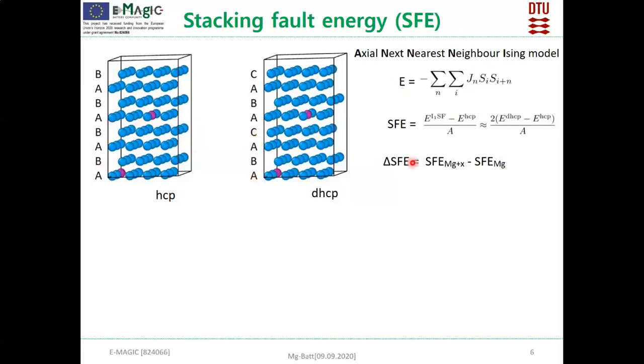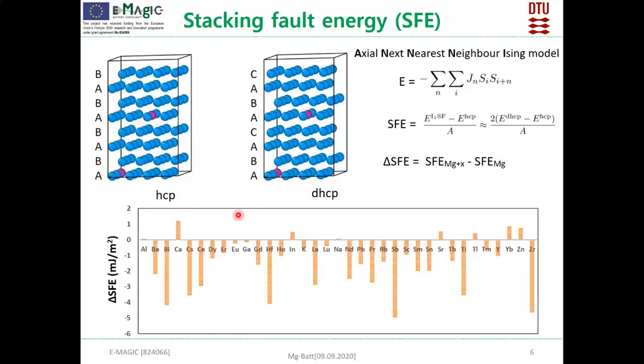And then we evaluated whether this doping is beneficial, whether it reduces the stacking fault, so we evaluated based on this term, and the results are shown in this figure. So based on our calculation, you can see most of the elements reduce the stacking fault. That means these elements reduce the stacking faults and in turn improve the ductility of the magnesium. And we see around 5 or 6 elements which increase the stacking fault energy.